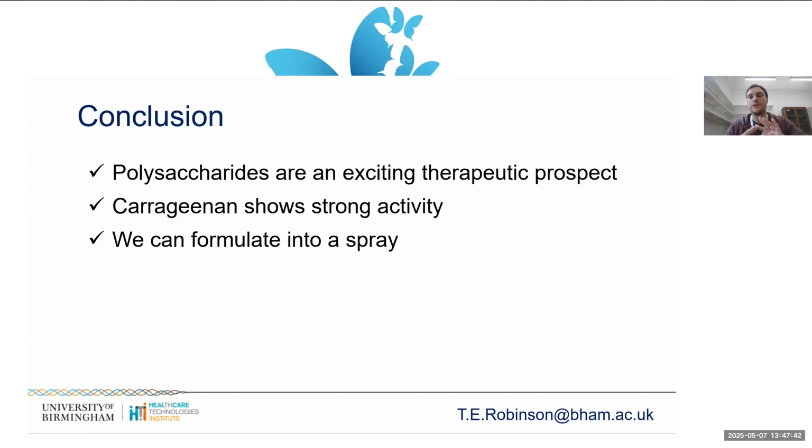So what people often do is they'll take that polysaccharide bulk material and put things like lipid nanoparticles in there. So you can encapsulate hydrophobic drugs, so drugs that wouldn't normally like to interact with water. And then you can change the properties of those nanoparticles to start changing the release rate of those drugs. So that's something we're very interested in as well, is how you control the release rate of some of these therapeutics. So rather than having a massive spike and then tail until you take more, trying to keep it more level. So yeah, absolutely, there's scope for that. So a lot of different possibilities to be explored.